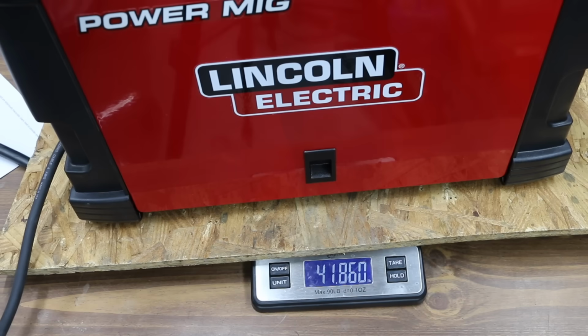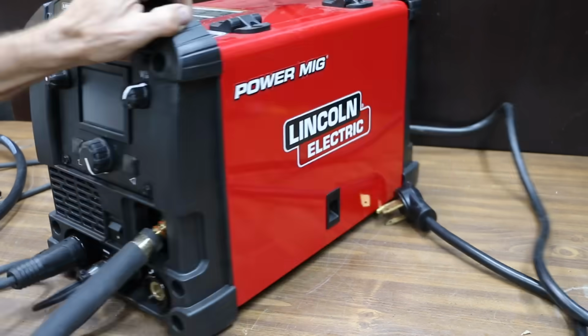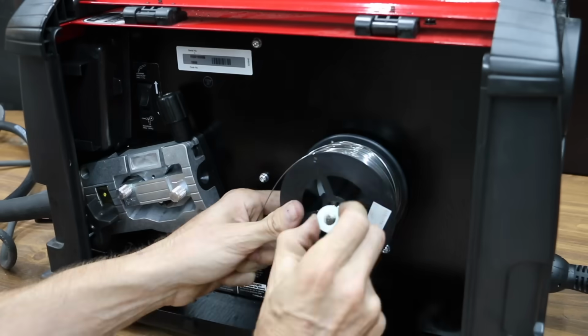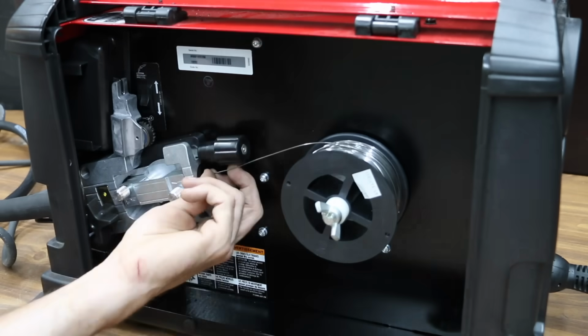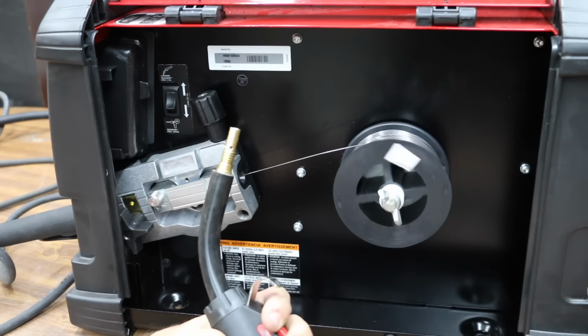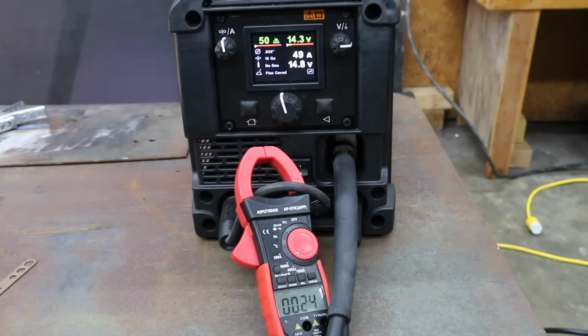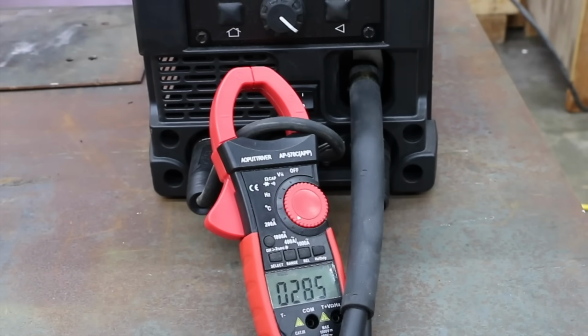Without a spool of wire on board, the Lincoln weighs just under 42 pounds. Just like the Vulcan 220, the Lincoln is a larger welder with plenty of space for installing the wire. Definitely an easy process to install the wire into the wire feed mechanism. And it's 21 to 49 amps of current on the lowest setting with the Lincoln. 281 to 285 amps of current on the highest setting.